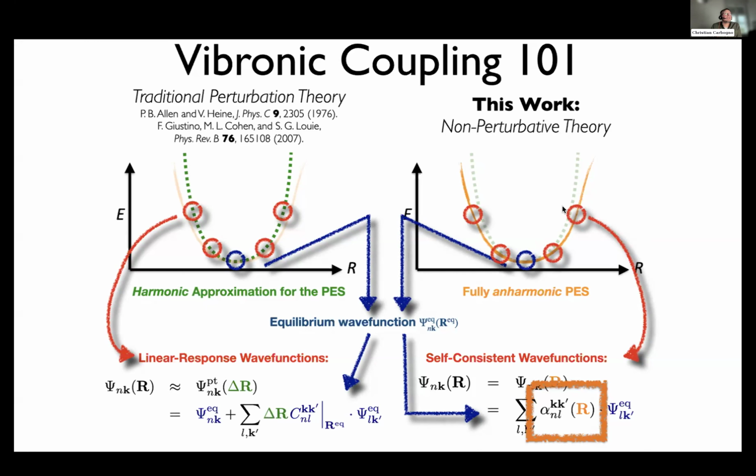This is a nice thing about this kind of ab initio MD approaches. In a defected system, you can just run your ab initio MD. Ab initio MD does not care about that, so you can include it without any problems. Still, it will be expensive, but it will not face the conceptual challenges of a frozen phonon or perturbative theory method that naturally requires some symmetry inside to even describe phonon dispersions and so on.